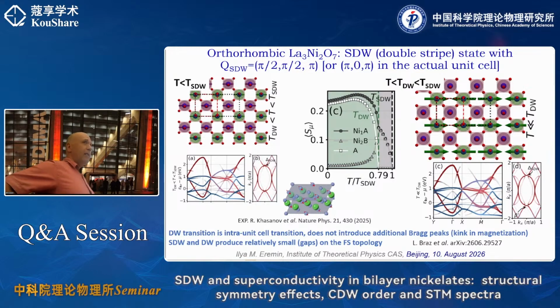So let me put it like this. If you analyze the corresponding charge instability, you don't see this. Usually, if you look at the paramagnetic state, suppose I start from a paramagnetic state, there I see a very clear instability in the spin density wave channel, because my susceptibility diverges at (0, pi). So that is the order that I set in. Then we knew from experiment that translational symmetry at the density wave transition is not broken.